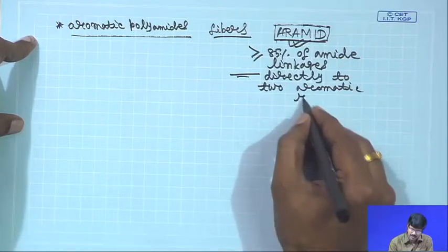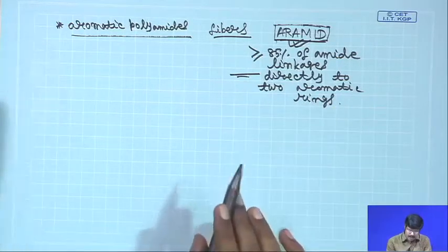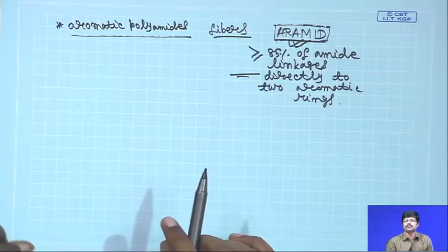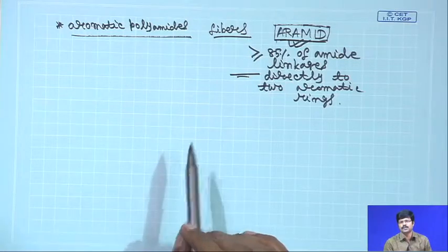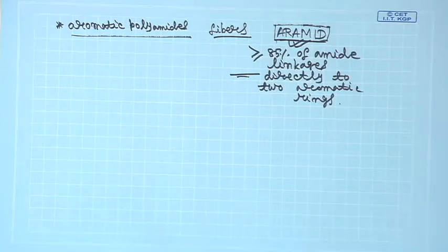Synthesis-wise it is quite different from how you approach the synthesis of aliphatic polyamides, because you are using a diamine and a diacid for the synthesis of the polyamide. So, it is basically an amide formation reaction. Now, in this case you have to use an aromatic diamine and an aromatic diacid. The thing is, the reactivity of aromatic diamines is significantly lower with respect to their aliphatic counterparts, because the nitrogen lone pair has to attack the carboxylic acid unit.